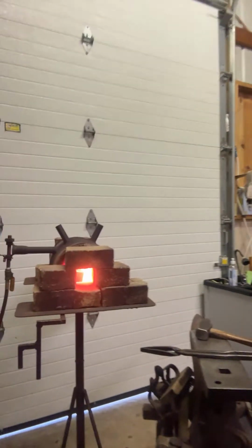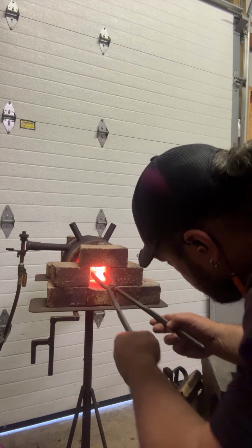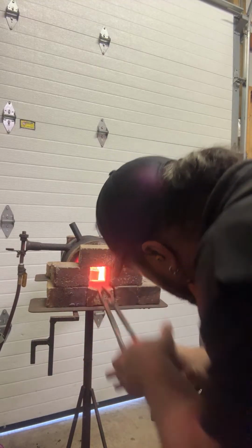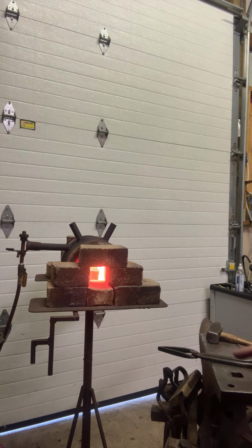The steel's actually coming up to temp nicely. I'm gonna give it a quick rotation. The billet does not have a handle on it. The billet ended up taller than my forge. Normally, when I'm forging out a bar, whether it's a mosaic bar or a random pattern bar, if I know how many pieces I want in my next stack, I knew I wanted 8, then I would say, okay, I know my clearance in my forge is like 4.5, maybe 5 inches. I like to stay at the 4.5 or lower. So let's just say I wanted the stack to be 4 inches.